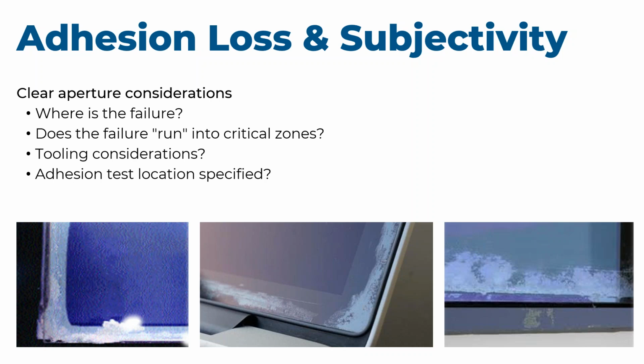The other place that if you measure tape adhesion is right at a tooling mark. Right at the interface of your tooling versus your coated optic is going to be the weakest point of your coating. If you can imagine, the conformal film goes over the metal and then right to the optic, and there's a break in the 2 layers when you remove the optic from the tool. If you then go and test this weak point, you could find some failure in this area. Now, the real test is if you continually test and the film doesn't continue to fail and run into the critical zone, then technically you should have a passing optic.